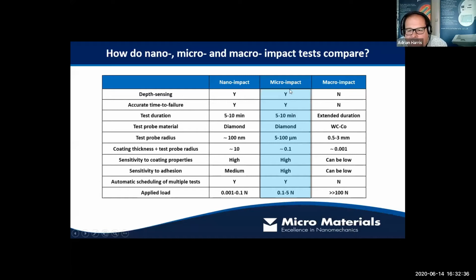Nano impact and micro impact both are depth sensing methods, so that means we're measuring the depth of the probe. Macro impact, on the other hand, what we tend to do is run the macro impact test and then perform microscopy at the end of the test as a post-test analysis. With the depth sensing methods, we're looking at time to failure. It's very, very clear when we get a failure event in an impact test. We get a depth step. We get an increase in depth. We'll see that shortly. So it's unambiguous usually to identify. So we can pick a time to failure.